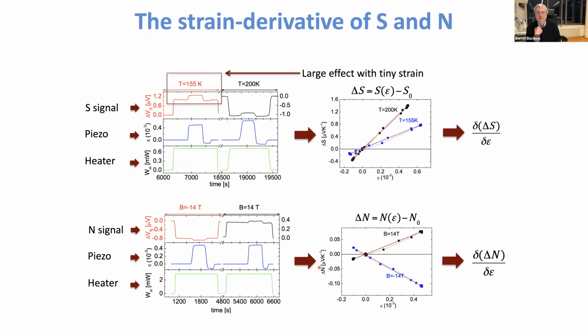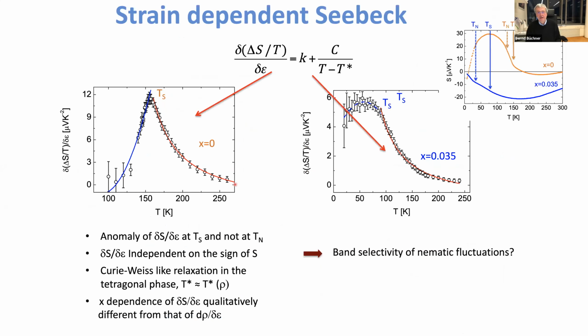So why does this behavior happen here? We have the sign change of the thermopower, but the nematic susceptibility shows the same sign. So it's really orbital selective. It's really related to one part of the Fermi surface only. And this, if we do some more realistic modeling of it, could give us an idea how the intrinsic mechanism of these things comes up. But at least it looks like it's not spin driven. I would say this looks more like orbital driven, yes.